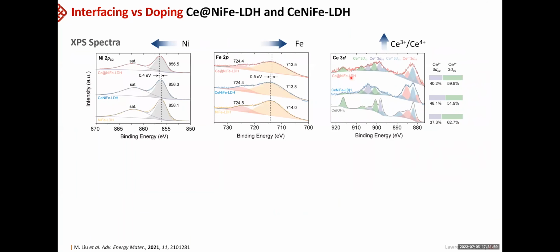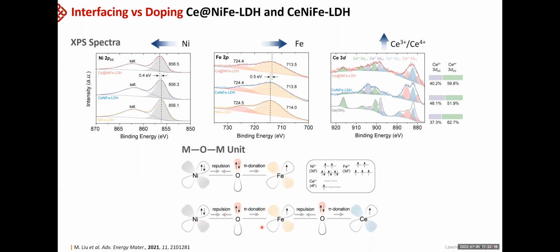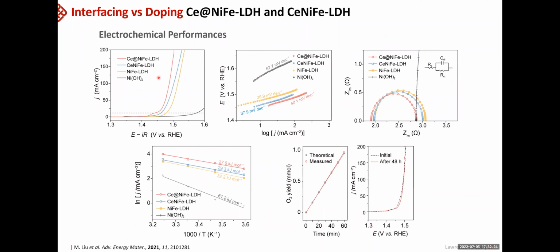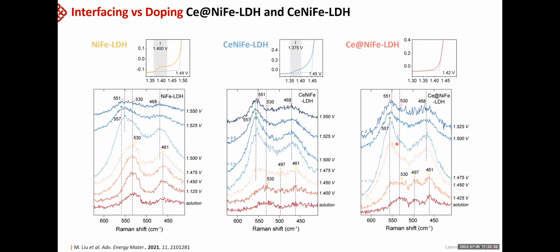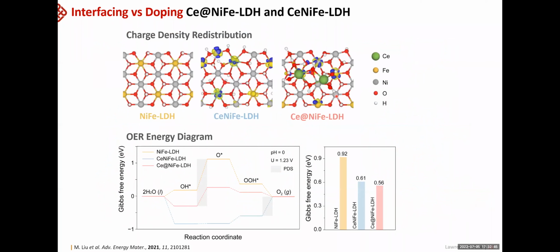What we found from the XPS spectra is that there's a shift in opposite directions between the nickel and iron, and also there is a more increased species of the nickel 3 pluses when we have the interface, which explains that there is a very strong electron interaction between nickel and iron, which is induced by the interface cerium species. From the electrochemical assessment, we saw better performance from the interface sample. And we analyzed that with in situ Raman, also we see that the conversion to the active species occurs at a lower potential. And from the DFT calculation, we also see that even the rate determining potential step has been shifted from the original position. So that explains much better performance of the interface sample.